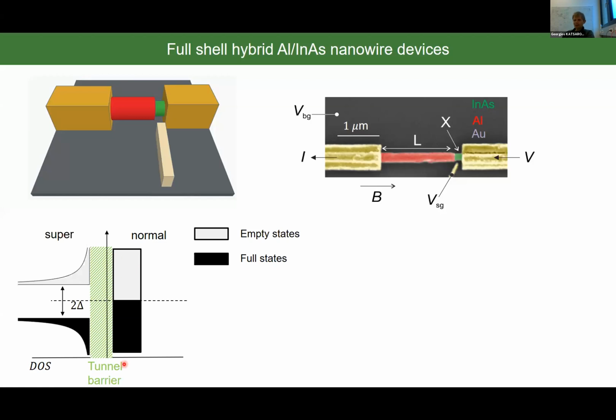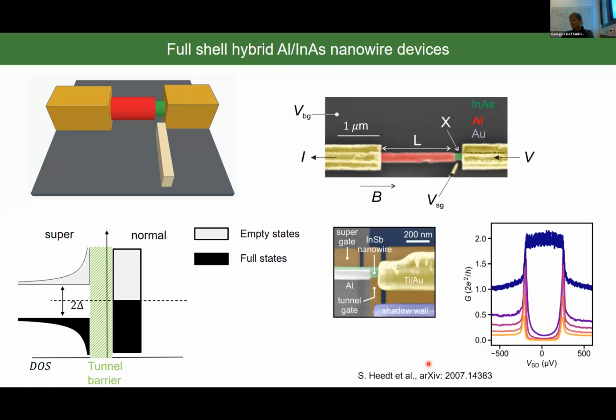So practically we have a normal metal, which is separated by a tunnel barrier from the superconductor. And by changing the bias voltage of the normal metal, we can have tunneling when, for example, the full states of the normal metal align with the empty states of the superconductor, and we can map out the local density of states of the superconductor. Important to point out is that the transparency of the tunnel barrier plays a big role, because you can either do tunneling spectroscopy or Andreev spectroscopy if your tunnel barrier becomes very transparent. And this has been beautifully demonstrated in a paper from Delft very recently, in which they have shown that by changing the potential on the tunnel gate, they can go from the tunneling spectroscopy regime to the Andreev spectroscopy regime.